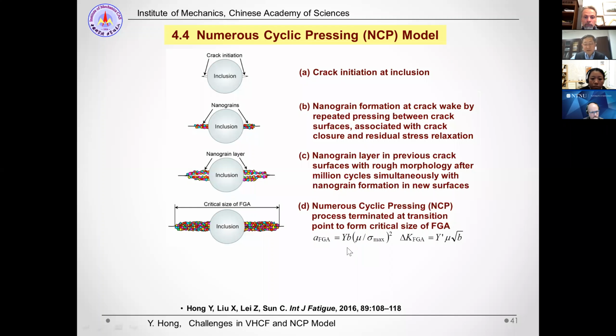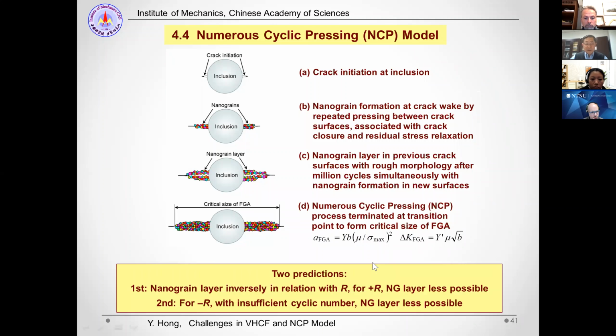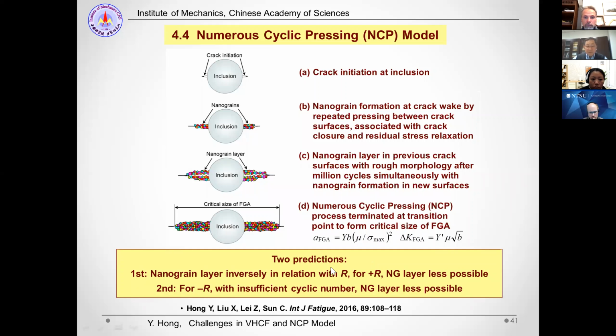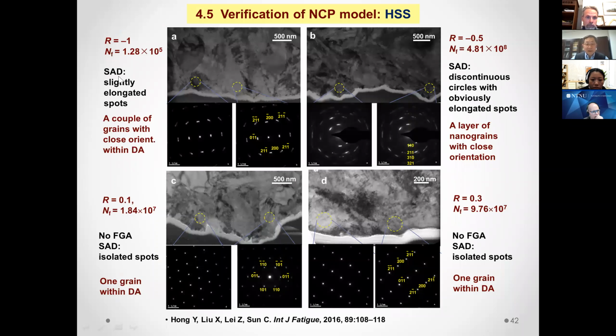of the size of the FGA, and also the delta K value of FGA. So for this model, we may have two predictions. First is nanograin layer will be inversely in relation with the stress ratio. For positive stress ratio, nanograin layer will be less possible. The second one is even for negative stress ratio, but the loading cycle is insufficient, the nanograin layer will be less possible. So we perform some further tests, and this one is -1 stress ratio.